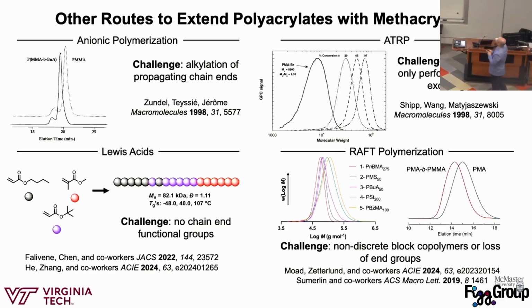If we look at RAFT polymerization, this is the example that I just showed. The only other example that is really present is from Moad and Zetterlund, where they can make these multi-block copolymers, and they get pretty good shifting in molecular weight to the right. And you can see they go from a methacrylate to a styrenic, to an acrylate, to a styrenic, to a methacrylate. They actually trick the system though. They don't make discrete block copolymers.